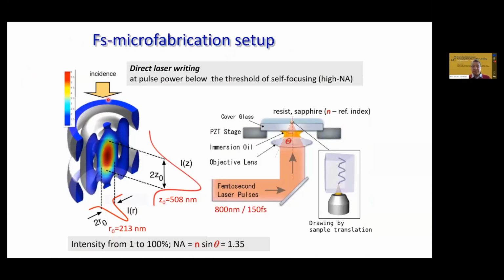The technique itself is very simple. So you have your laser beam, you tightly focus it on your samples. At the very beginning, it was always with the spirit of polymerization, you need very tight focusing in your resist. But in fact, that tight focusing uses oil immersion way of focusing inside resist, which is less practical. So you can still focus your femtosecond pulses inside transparent material or on the surface for ablation or modification. And with the tuning of intensity for modification threshold, you really can localize what you are writing with a very, very high precision, and it can be sub-diffraction limit.